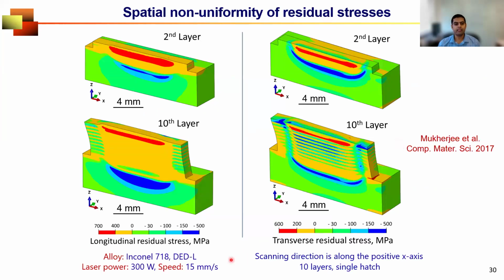Similarly, for residual stress, we can get the spatial distribution of residual stresses, like how the high residual stresses that are accumulated after the deposition of the second layer are partially alleviated when you deposit a subsequent layer and reheat and recool it, and how residual stress is spatially so non-uniform, causing delamination, cracking, and many other problems in additive manufacturing, and how a numerical model can capture all of those elements and guide engineers to overcome all these problems.